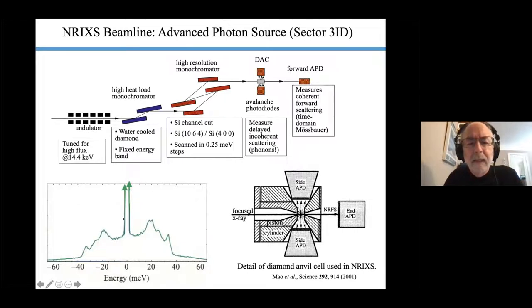Now we can actually get the nuclear resonance to occur even if we're off this perfect resonance energy, if we create a phonon and bring the energy down to be resonant. And this gives us a good measurement of the number of phonons of those energies, or we can annihilate a phonon.